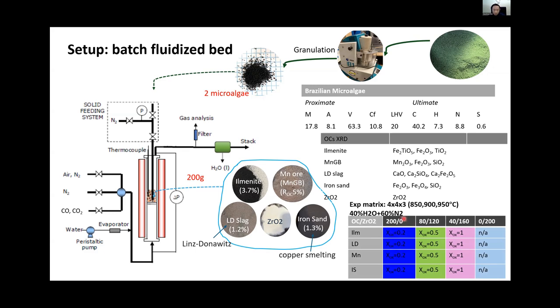So the oxygen carriers are mixed with zirconia, but were reduced to 0.2 or 0.5 to maintain the available oxygen in the bed. This is to rule out the effect of available oxygen in the bed. And three temperatures, 850, 900, 950, were used in the tests.